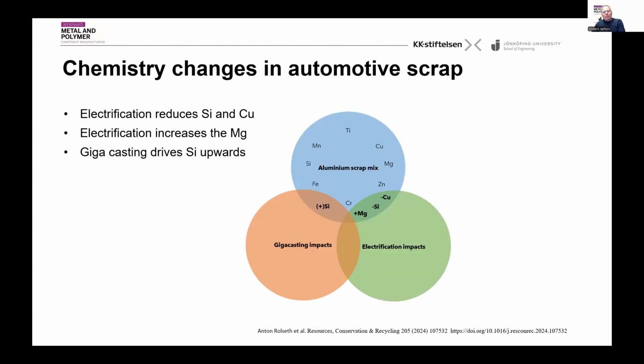the conclusion is then that we have a number of alloying elements in the aluminium scrap mix. And if we just look at the electrification, we have less copper, less silicon, but more magnesium. And what we remember now is that magnesium was one of the elements that to a large extent put a limitation. So if we put scrap back into our alloying element cycle, into the alloys, that means that it will be even more limiting because you would have an increment in your magnesium content. Now, gigacasting will not really strongly affect that, but we will put some silicon back into the system. And there's a window here now. So if we start using alloys that have less silicon, we can also reduce the carbon footprint. And so this is an interesting concept.